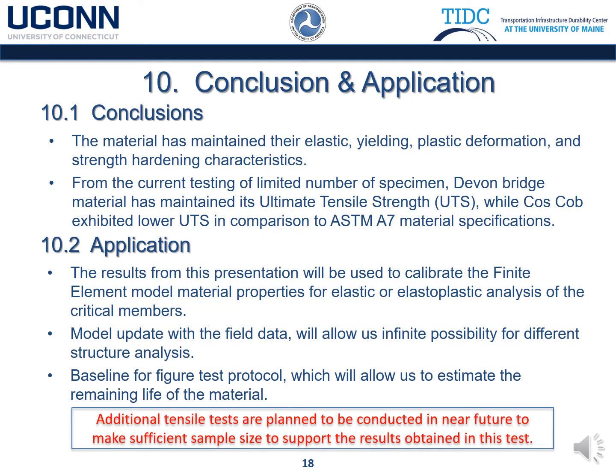Conclusion and application. With the presented results, we can conclude that the test material has maintained its elastic, yielding, plastic deformation, and strain hardening characteristics. With a limited number of specimens, Devon Bridge material has maintained the ultimate tensile strength, while Cos Cob exhibits lower values in comparison with the ASTM A7 specification.